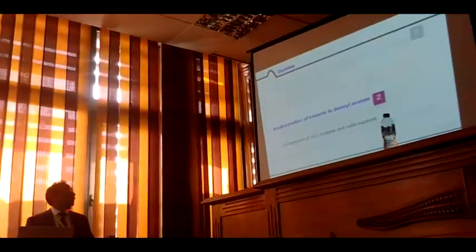On the whole, we can conclude that the loss of palladium oxide, loss of antimony, and the migration of carbon species are collectively responsible for the deactivation, so that by 350 you are not able to regenerate.